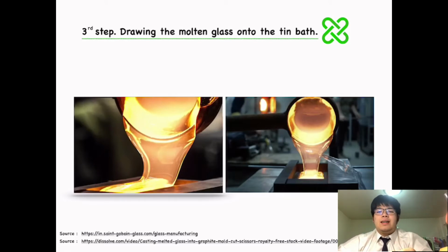Ribbon thickness in a range of 1.9 mm to 19 mm can be achieved. The glass, which is highly viscous, and the tin, which is very fluid, do not mix, so the contact surface between these two materials is perfectly flat, giving the term flat glass to the final product. Right, let's move on to how is glass made by Gomin Chompibun.